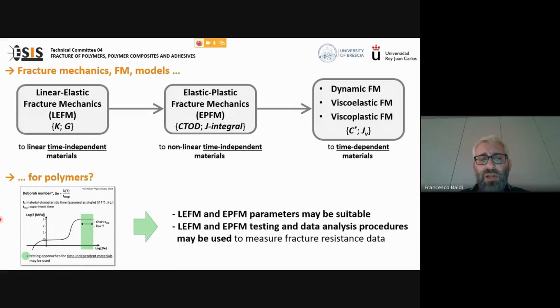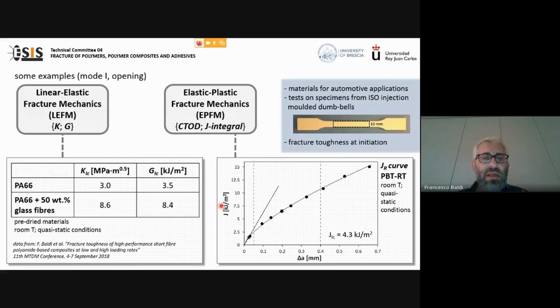In this graph here on the left, I refer to an amorphous polymer simply because it is simpler to describe, but similar consideration may apply also to a semicrystalline polymer. Now, just to give you an example, in this slide, I have reported some fracture toughness data obtained in mode 1, fracture opening mode, on polymers according to the linear elastic fracture mechanics and to the elastic plastic fracture mechanics scheme. In this box on the left, we can read data of K1C and G1C.